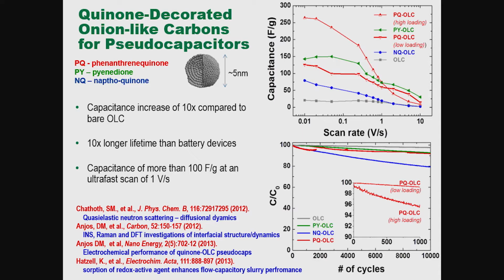So this is the capacitive behavior of the bare onion-like carbon electrode surface, and here is the capacitance after being loaded with various quinones. We've published a number of studies on that, and this pseudocapacitive behavior is advantageous in the sense that cycle life is very good, just like a capacitor. This is 10,000 cycles, and you see very little fade in performance, yet we're boosting up the energy storage.